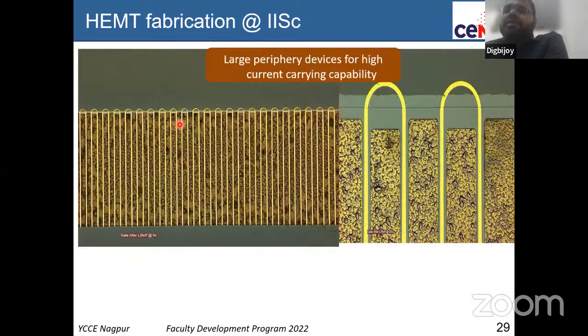However, to actually make a power electronic circuit, you need larger devices so that they can carry very high current, like 5 ampere, 10 ampere, 20 ampere, 30 ampere. Those are very high currents, and for that, you need large devices. So what you see here is a very large device. If you zoom in, then these yellow winding circular kind of things are actually gate fingers. So there's a gate between source and drain. So this is source, drain, source, drain, source. It will continue source, drain for maybe 50 times or 100 times, so that the gate winds back and forth. Eventually the gate will be very large, like a millimeter, or 50 millimeters, 200 millimeters. So the large width of the gate will enable you to carry larger current.